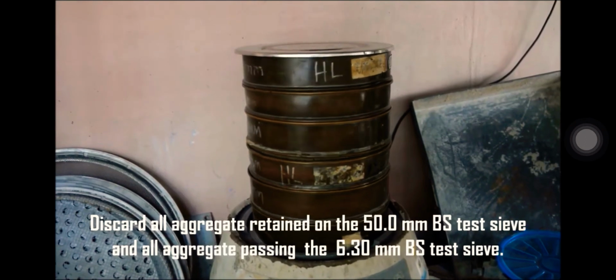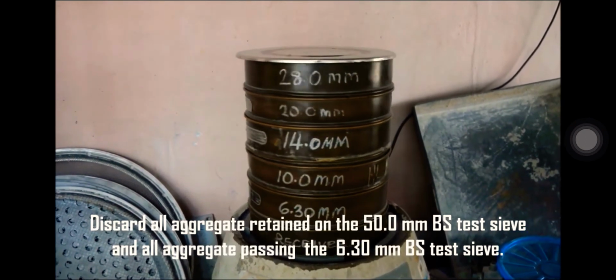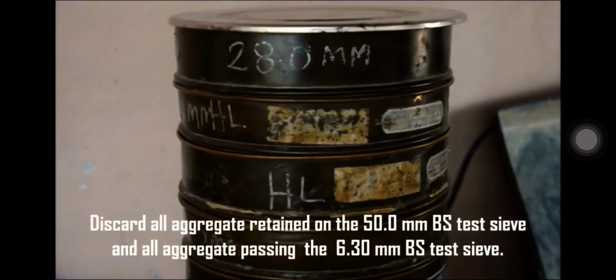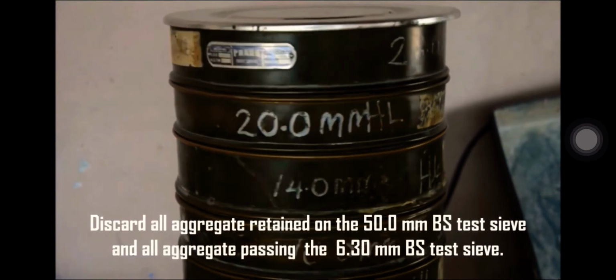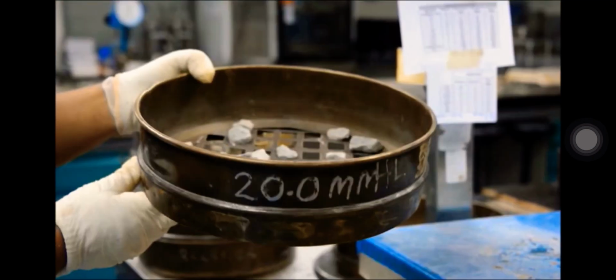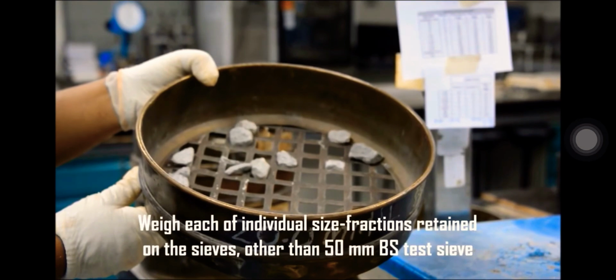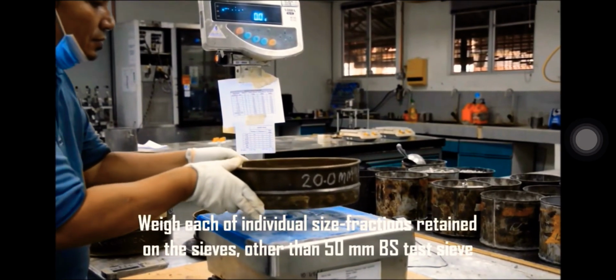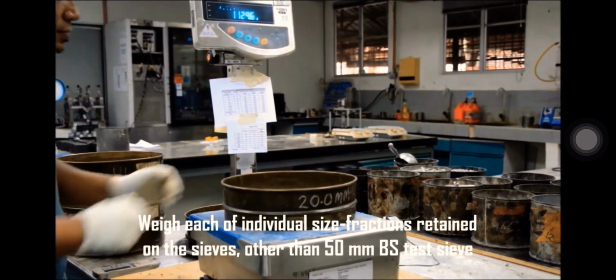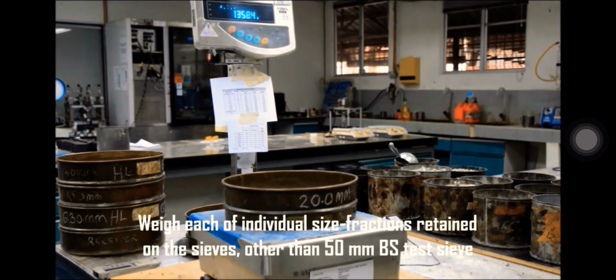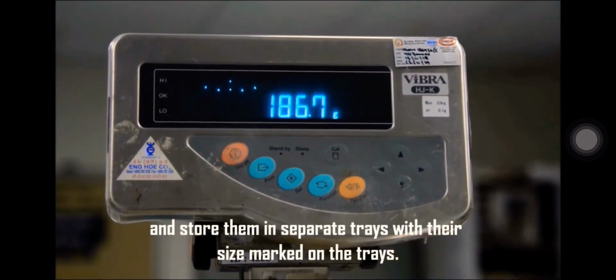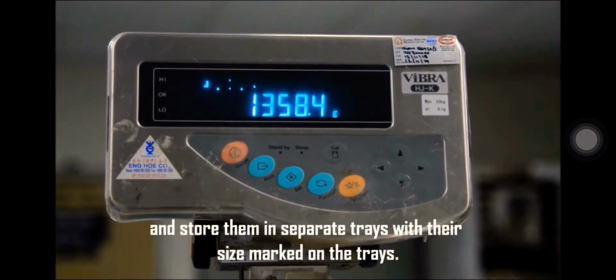Discard all aggregate retained on the 50 mm BS test sieve and all aggregate passing the 6.30 mm BS test sieve. Weigh each of the individual size fractions retained on the sieves other than the 50 mm BS test sieve and store them in separate trays with their size marked on the trays.